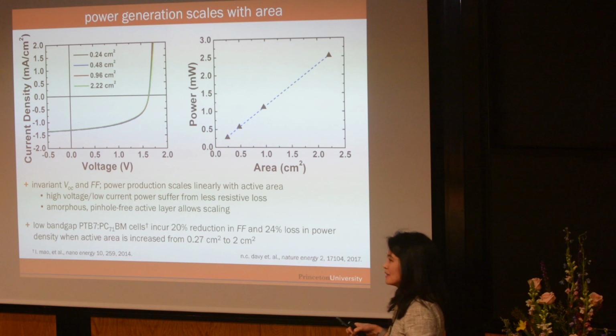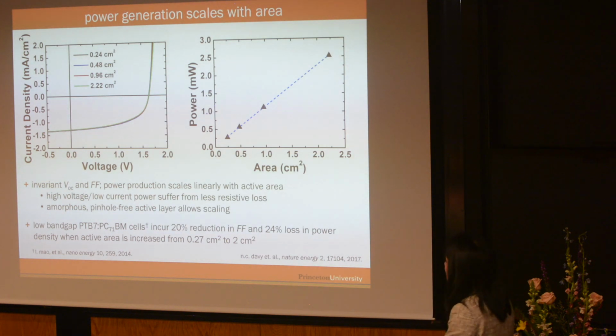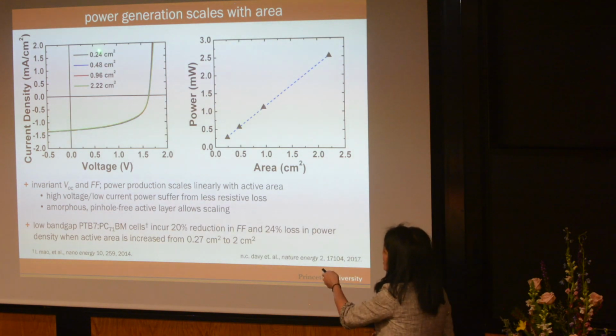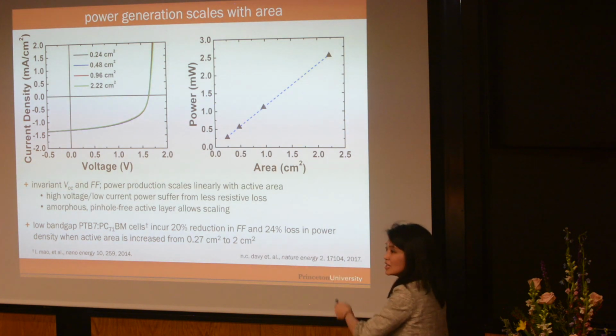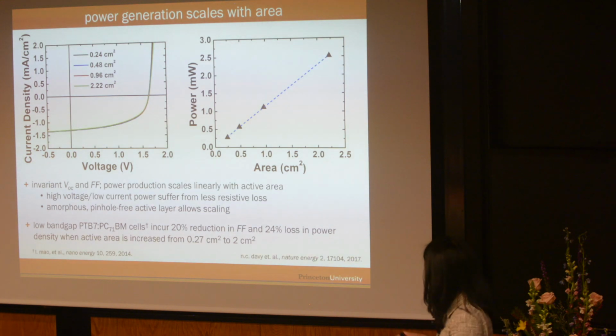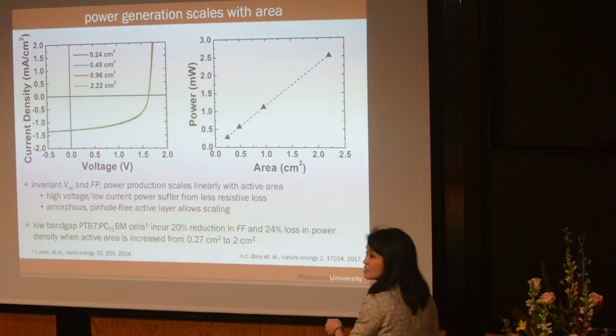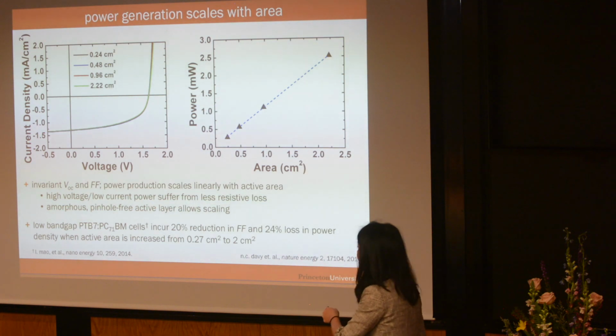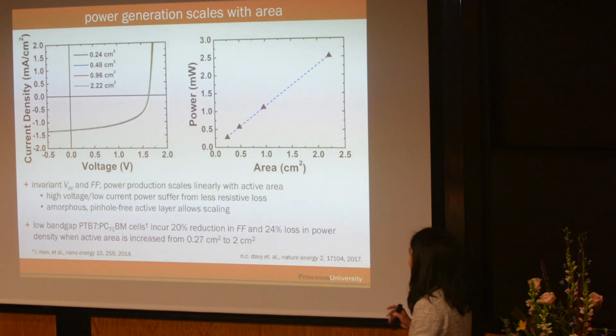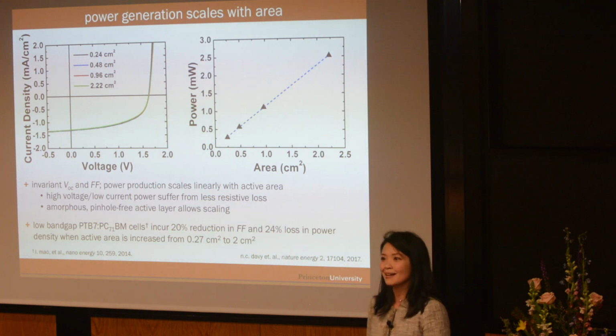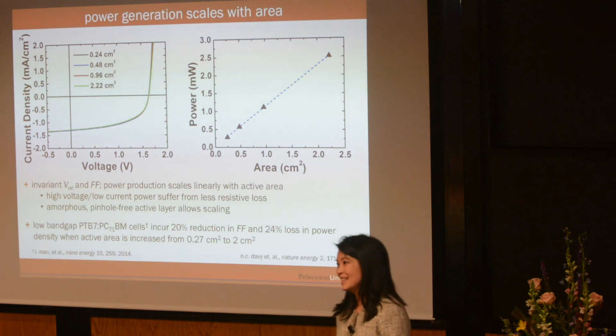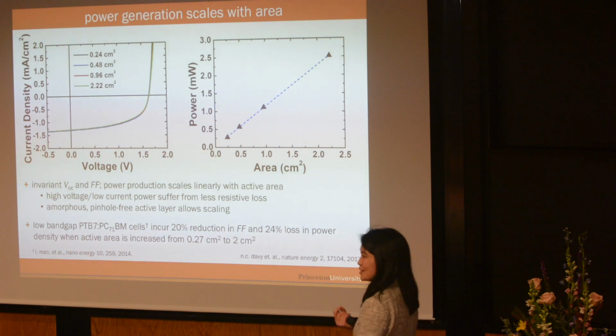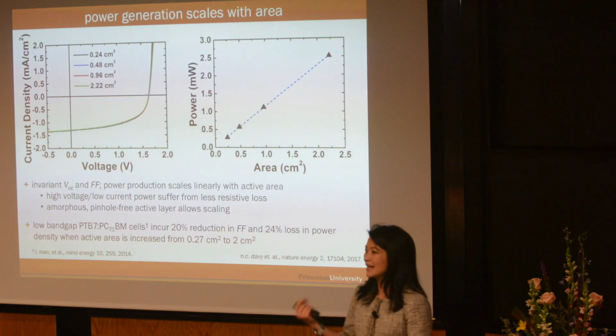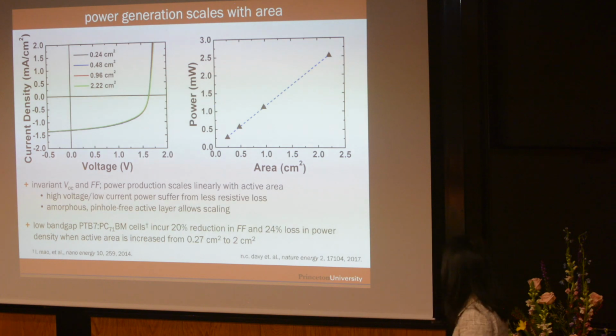There are no holes, right? There are no pinholes. There are no grain boundaries, no pinholes. And so because there are no pinholes, we can increase our cell size, and you can see that the current density as a function of voltage just lie right on top of each other. If you plot the power as a function of area, it's linear. Okay? It's really nice. And also, there's another factor that I should talk about, because, again, our cells produce so little current, and parasitic resistance scales as the current squared. So we suffer less from parasitic resistance as well. Okay? So this was a win-win situation for us.